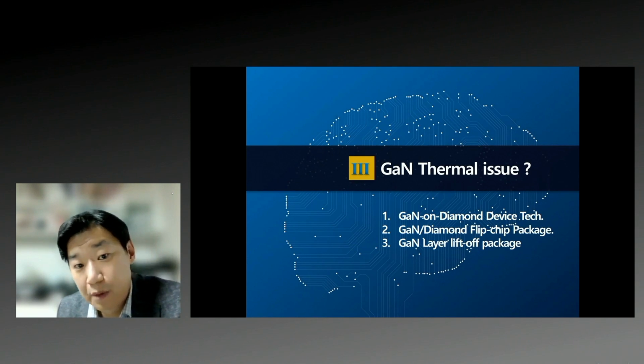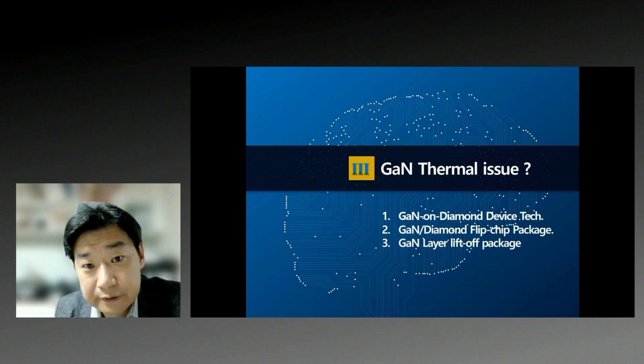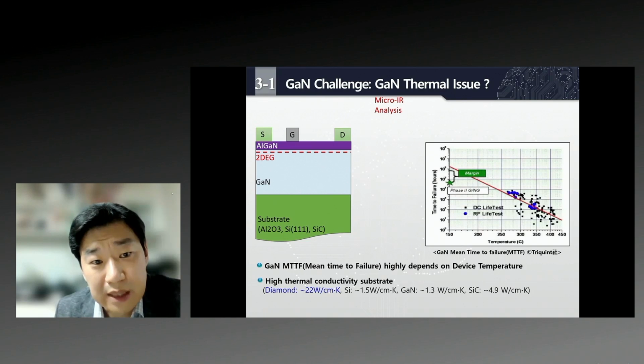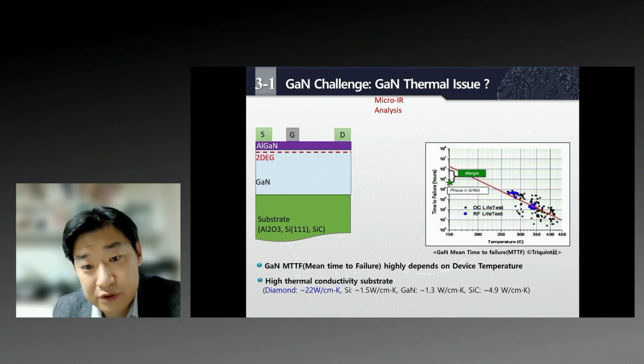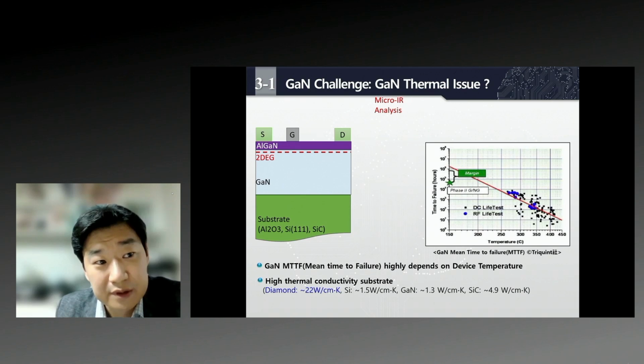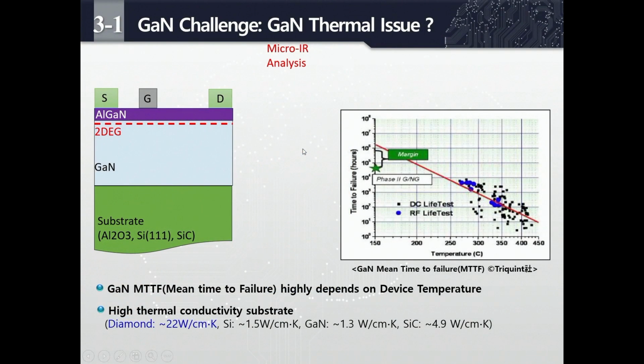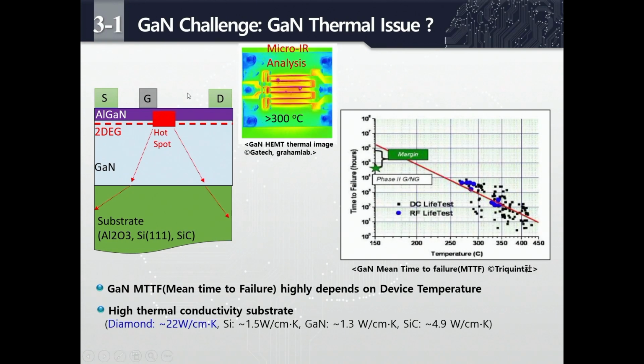So I will talk about some GaN thermal issues. I talked about gallium nitride switching characteristics and RF characteristics. GaN handles high current and high voltage. But the problem is that it has very high junction temperatures. Typically below the gate, around the surface area, it has hotspot zones. Sometimes it goes to more than 300 degrees Celsius, when you do micro-IR analysis, showing very high temperature areas.